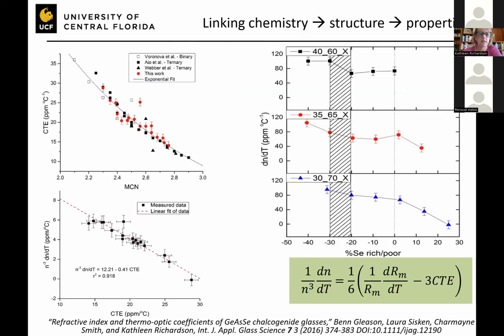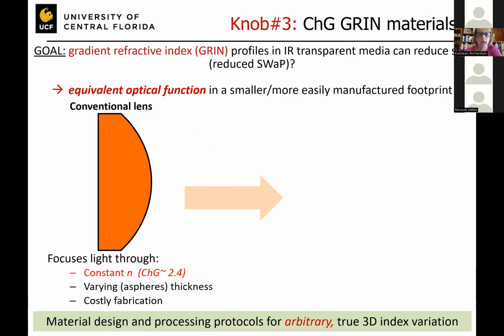Now, I mentioned in this, we can change the refractive index by changing the ingredients, the composition. And that's fine if we want to make a single element material, because the way we change how this lens works, for example, here's a typical cartoon of a lens where it's a homogeneous material. Refractive indices of chalcogenides are on the order of 2.4. The way we change focus is typically through changing the shape of this curvature of this lens.